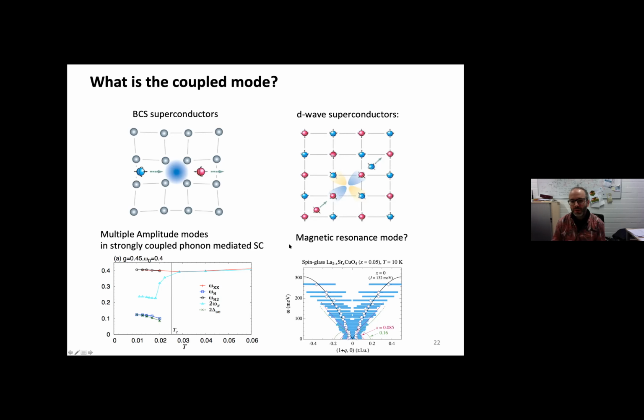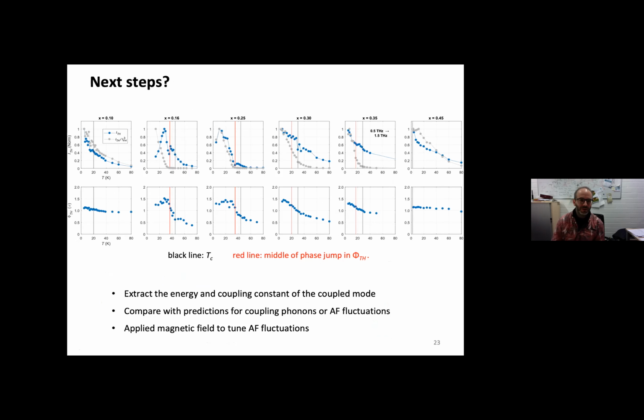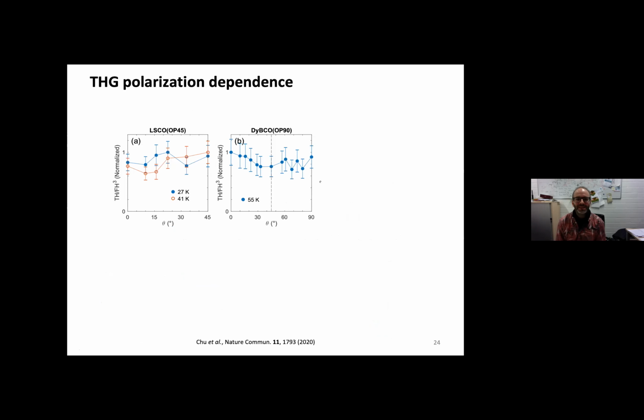But now future experiments really have to show what's really going on in these materials. So next steps would be now to also do magnetic field dependencies of these, and maybe at the very end, if someone is interested, I can show first hints on what a magnetic field dependence of these phase jumps would look like. And a big discussion, of course, that comes up if you're dealing with high-field driven superconductors is always, is this response really due to the superconductor itself, or are you exciting hot quasi-particles? And then if you just drive a very strong current, there is no reason why this current should not show up in a THG response as well.